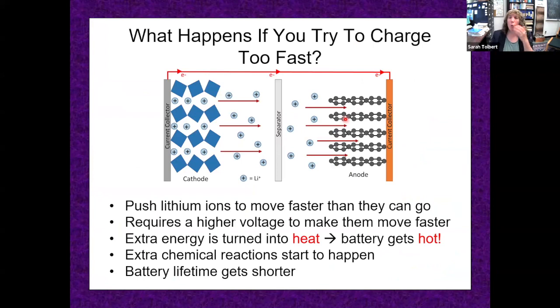Okay, so what happens if you try to charge it too fast? I said that the reason the lithium moves is because you've created an electric field. If you want to try to make the lithium move faster, you need to use a bigger electric field, which means applying a bigger voltage. But the energy of that bigger voltage is not used for your battery. It's just wasted as heat.